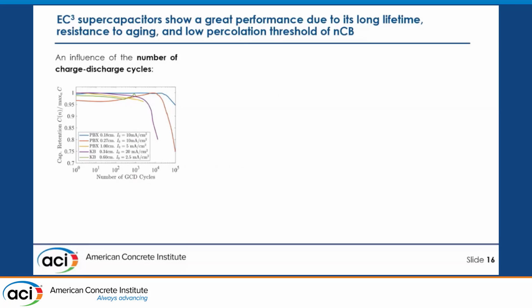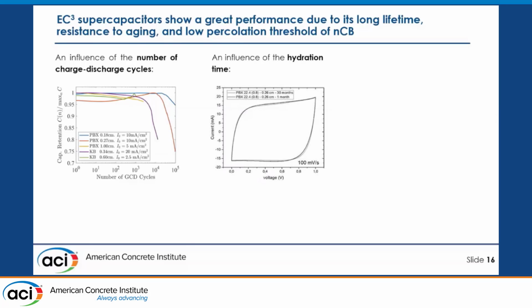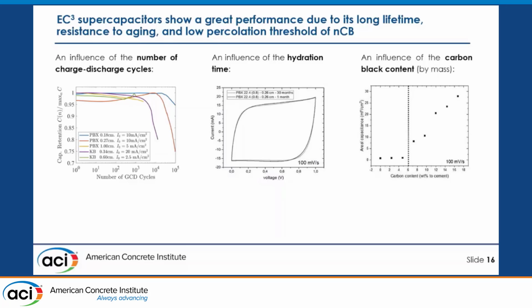When we talk also about supercapacitors and battery technology, there are different aspects that we have to keep in mind. For example, how the retention of the capacitance goes with the number of charge-discharge cycles. So we were able to reach more than 10,000 cycles without losing a lot of the capacitance. Usually that drop was associated with drying of not properly sealed samples, so that was not the other issue. Also, how hydration time can affect the capacitance. Tests performed after 1 month and 30 months showed comparable capacitance, which is also extremely important.